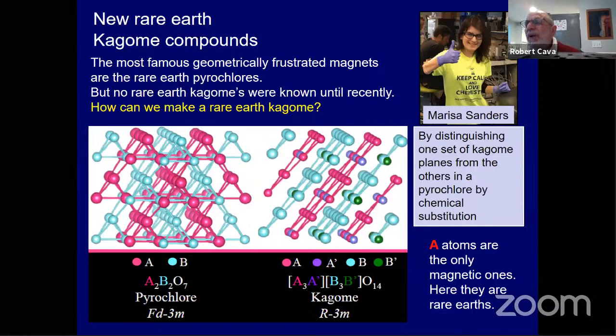And you can directly test the relationship between rare earths on a pyrochlore lattice and rare earths on a Kagome lattice by adding an extra atom, which forces this lattice here, which is the pyrochlore, to become a Kagome by putting non-magnetic atoms in between every set of magnetic atoms. So instead of having the magnetic atoms infinitely connected, you separate them. It's difficult to do this, but you can put the same rare earth on the Kagome lattice and the pyrochlore lattice, and then just test which one is more frustrating.